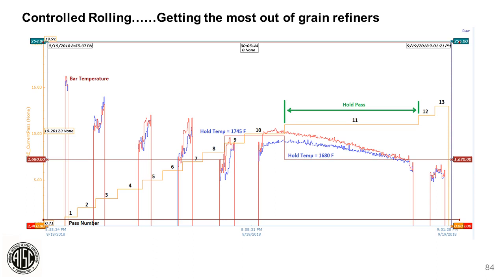Now this is an example of some of the instrumentation or some of the data that can be collected in a modern steelmaking process. These pass numbers are denoted. For example, pass 1 is that beam blank moving north in the universal rougher edger mill. Pass number 2 would be that beam blank moving south. In each case, the gap has gotten narrower on the horizontal and vertical rolls. Pass 3 is the bar moving north again. Pass 4 is the bar moving south. These red and blue lines denote what each flange temperature is. So you'll see that there are points where there's no temperature being taken because that beam blank is simply moved out of the way of the thermal imagers.